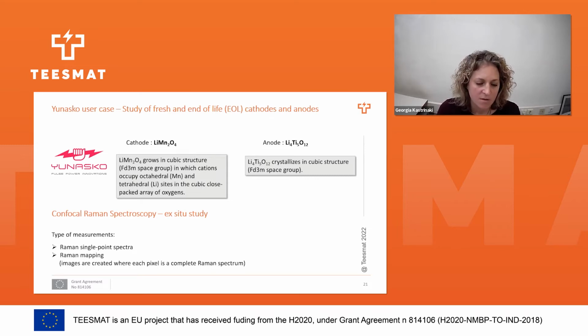Now we studied these materials ex situ, which means that we received fresh and also cycled cells which were dismantled. They were coin cells that were dismantled and washed out with different solvents. So we received cathode and anode electrodes, and we measured them under the Raman with single point spectra. And also we performed Raman mapping, which creates chemical images related to different peaks of the Raman spectrum.